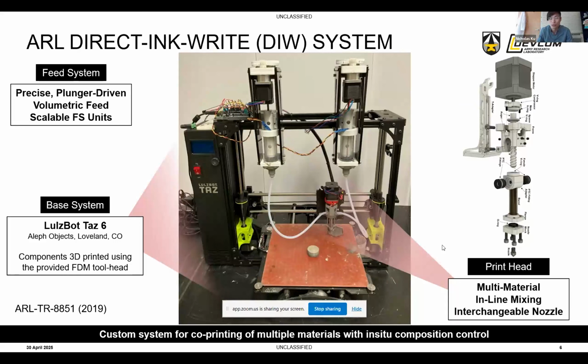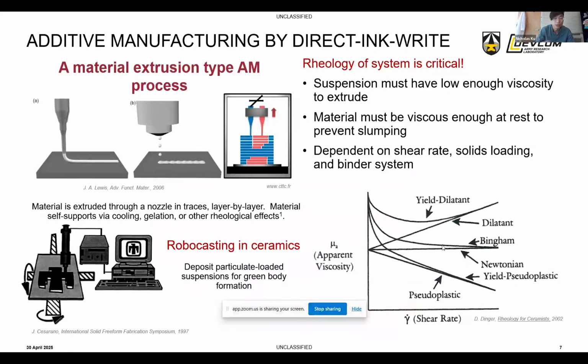And what happens is you'll have 2 materials entering the same barrel, and we have a 3rd stepper motor spinning an auger that helps provide conveyance, but also inline mixing. So now we have in situ composition control, right? Depending on what ratio we deliver down through the feed system, we could print all material A, all material B, or any combination of the 2 as we move through the print.